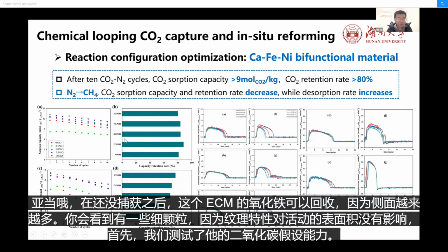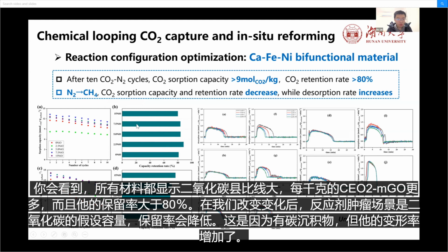For the reactivity, firstly we tested its CO2 sorption capacity. You will see that all the materials show a CO2 capacity larger than 9 mol CO2 per kilogram, and its retention rate is larger than 80%. After we changed the reacting agent to methane, its CO2 absorption capacity and the retention rate decrease. This is because there's a carbon deposit, but its desorption rate is increased.